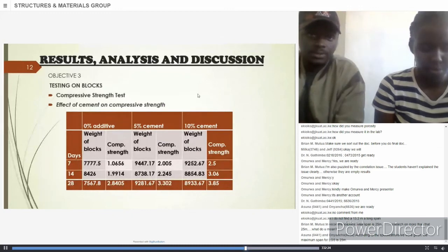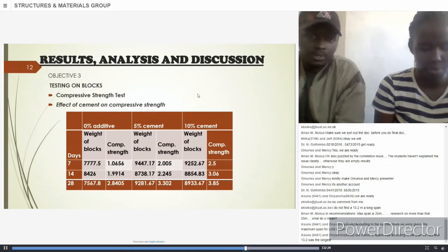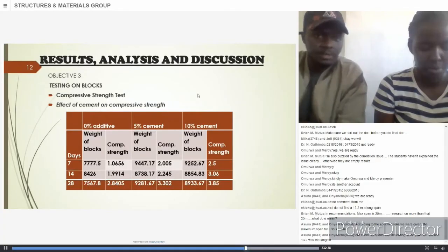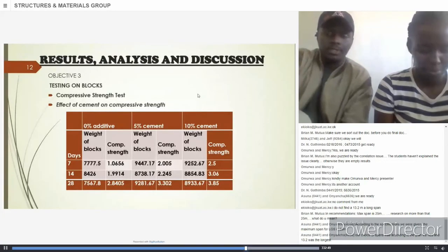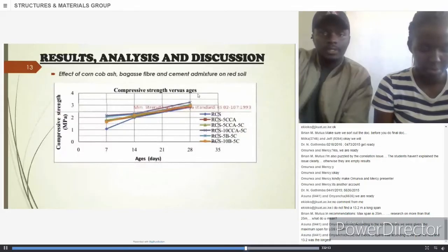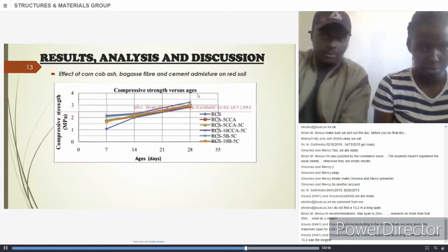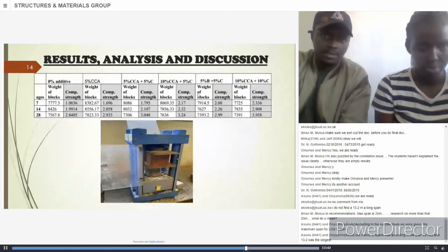And to our next objective, which was objective number 3, we were to test the blocks and determine the compressive strength. In this sector, we had 2 variables, which were cement and corn ash as the main materials which are supposed to vary. The table shows the red soil compressive strength without any addition of any stabilizer, as well as with cement in different proportions, 5% and 10%. And there's a graph which shows the compressive strengths of the different compositions of blocks we made, and a table which shows the same.